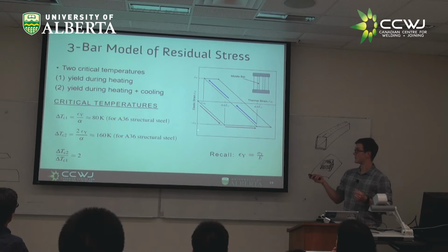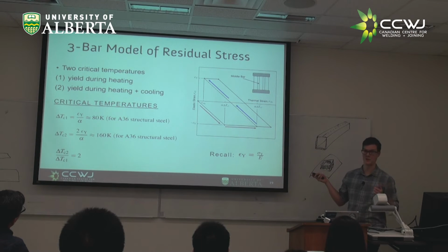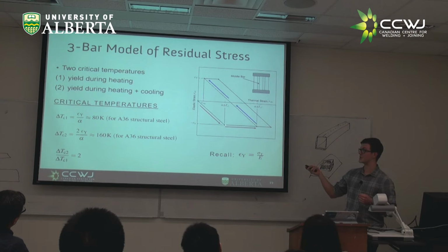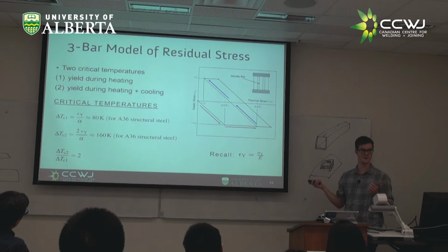Now, in practice, if we use this elastic perfectly plastic model, we actually don't even have to worry as much about what these temperatures are, because we're going to see it's the ratio that becomes really important. And it doesn't actually matter how strong your material is or what's going on. As long as you have this elastically perfectly plastic assumption, you're always going to have a ratio of this point to this point that's 2. That's because we have to get to 1 yield strain here, and here we have to get back to 0, back to a second yield strain, so it takes twice as much temperature change. So the ratio between this peak temperature, where we have yield magnitude residual stresses, and this peak temperature, which divides a region of no residual stresses from some residual stresses, is always going to be about 2.